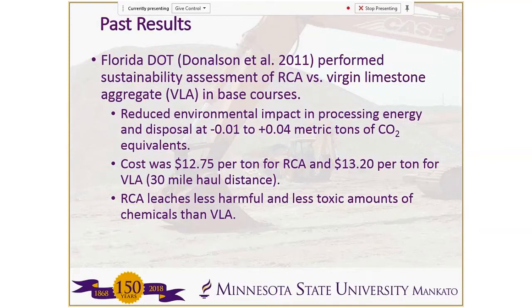Okay. Moving on to some of the sustainability aspects, looking at first the economic aspects of this. Some of the past studies that were done, in Florida DOT, they did an assessment of recycled concrete versus limestone aggregates, but they were looking mainly for the use in base courses. So they found a reduced environmental impact in the processing energy and also in disposal. So the RCA had a better environmental performance. As far as the costs, they found about $12.75 per ton for RCA and $13.20 for the limestone aggregates. They also assumed a 30-mile haul distance. Also, RCA was found to leach less harmful and less toxic amounts of chemicals than the limestone aggregates.